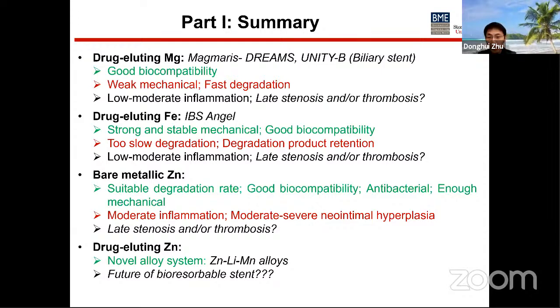For the drug-eluting iron, the latest is so-called the IBS angel. They showed strong and stable mechanical property, good biocompatibility. The degradation rate was a little slow, and the possible degradation product retention over a long period could be a concern. Inflammation was low to moderate. Same as magnesium, late stenosis or very late thrombosis needs further evaluation.